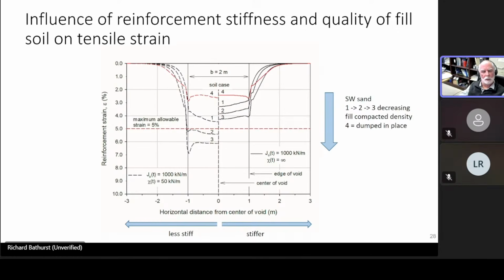So if we focus on well compacted to lower compacted fill cases, 1, 2, 3, you can see that the strain in the reinforcement is increasing as the fill quality goes down, again ignoring the dumped case. And then on the left hand side, we have the same fill but a lower stiffness material, and again you can see that the reinforcement strains are greatest at the edges, and we have situations in which we would not satisfy the 5% strain limit state.